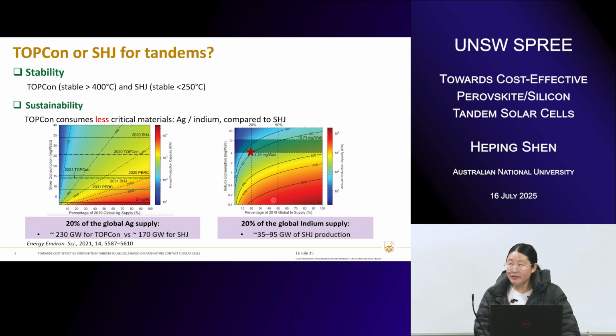On the other hand, for the other rare element, indium, we know that heterojunction solar cells use a lot of TCOs, which usually involve indium in the transparent conductive oxide material, which is absent in the TOPCon cell. So if we assume that 20% of the global indium supply will be used for making solar cells, unfortunately that poses another significant constraint on the production capacity of silicon heterojunction, to even less, around 35 to 95 gigawatt. So with that, from the efficiency, cost, stability and sustainability points of view, we see a clear advantage of using TOPCon cell technology compared to silicon heterojunction.